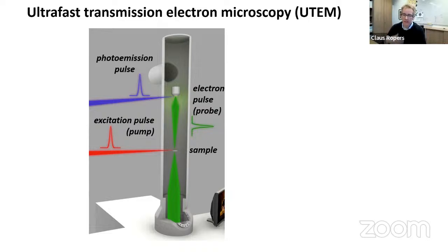So it's an optical pump electron probe technique where you start with a regular electron microscope with an electron source at the top and transmitting electrons through a sample, but now not in a continuous way, but basically in a pulsed way, such that the electron beam is pulsed. You produce flashes of electrons, which then allow you to take snapshots of the dynamical evolution of a sample, where the evolution is induced and triggered by an optical excitation pump pulse. So it's an optical pump electron probe technique, which essentially takes the temporal resolution from the laser side and the spatial resolution from the imaging capabilities of the electron microscope.